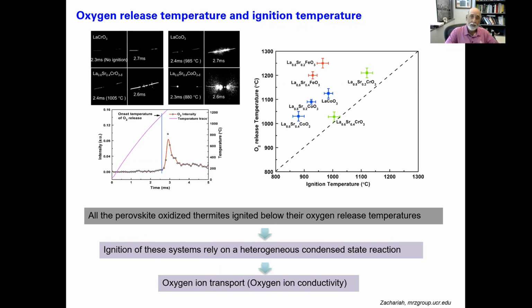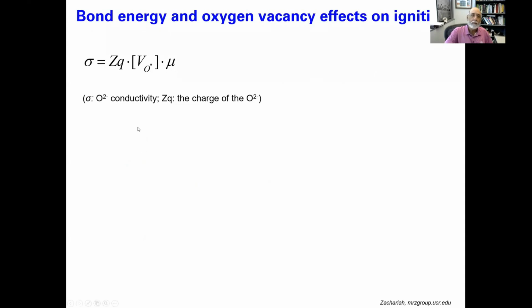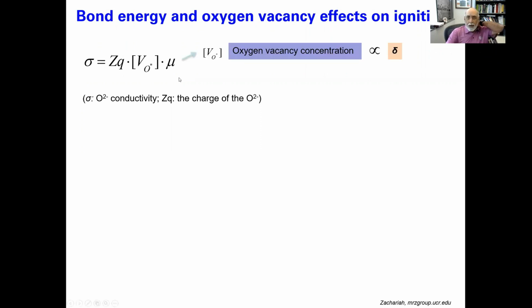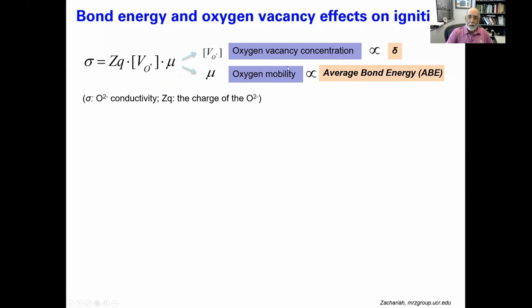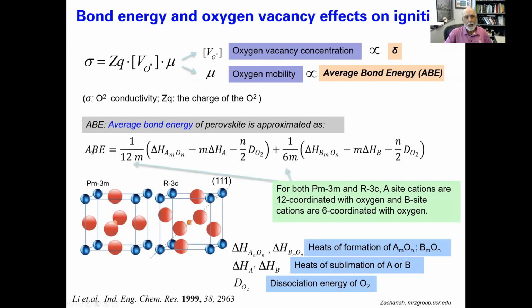So now we can make all these particles of all the same size, all the same crystal structure, and then we can see how they behave. So the oxygen ion conductivity, or movement of oxygen ions, is proportional to the vacancies, the places where it can hop to, and the mobility, how fast an oxygen ion can move. So those are 2 parameters that are important. And that we can vary by this delta parameter by putting strontium in to induce vacancies. And this is an intrinsic property. But we think that this should be proportional to the bond energy. The ability to move oxygen, I've got to break an oxygen metal bond, I should expect it to be proportional.